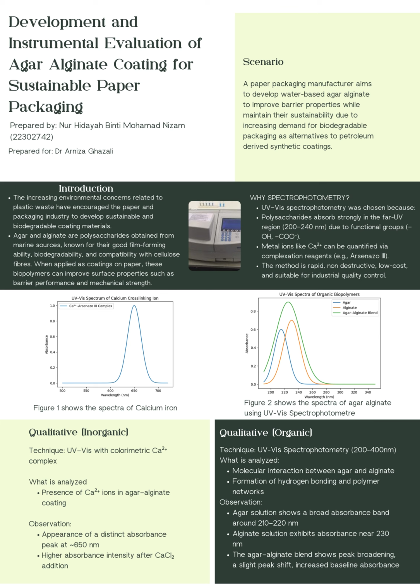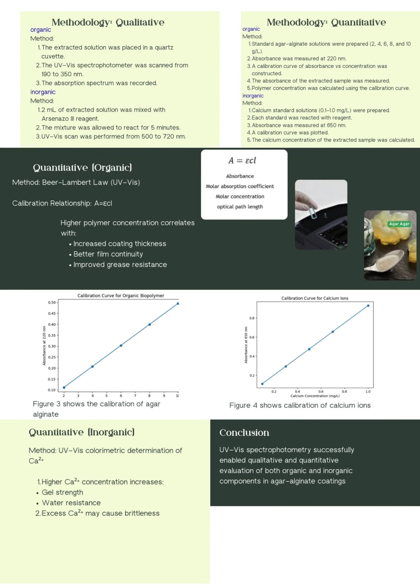Next, for quantitative organic analysis, agar-alginate standard solution was prepared and measured at 220 nanometers. A calibration curve was constructed based on the Beer-Lambert law, and using this calibration curve, the concentration of agar-alginate in the coating extract was determined. The higher polymer concentration is associated with improved film formation and coating uniformity.